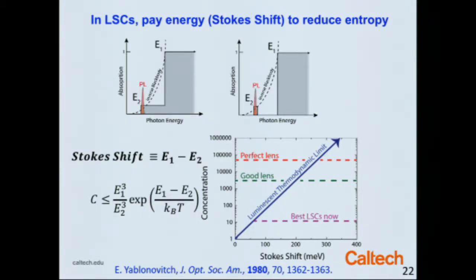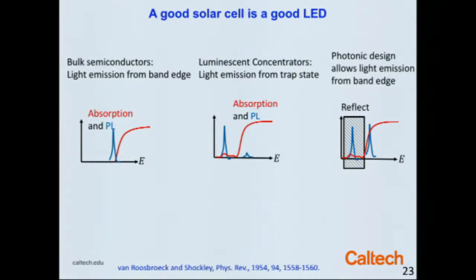It's quite interesting. The problem is right now the luminescence efficiency and the light trapping characteristics have limited us so far to concentration factors in the range of 5 to maybe 10. So this is what we're trying to change.